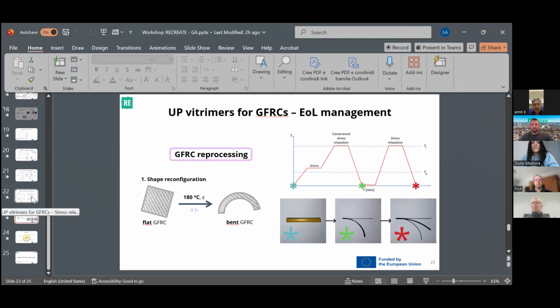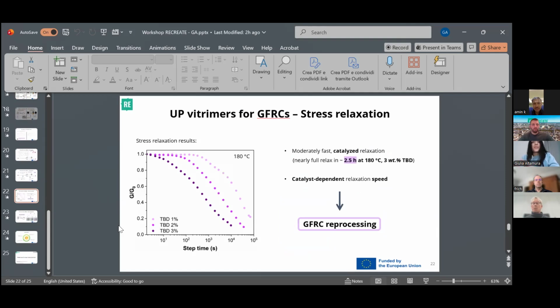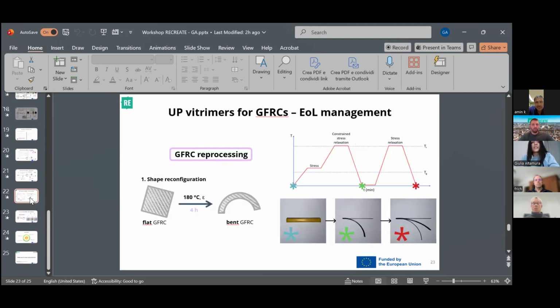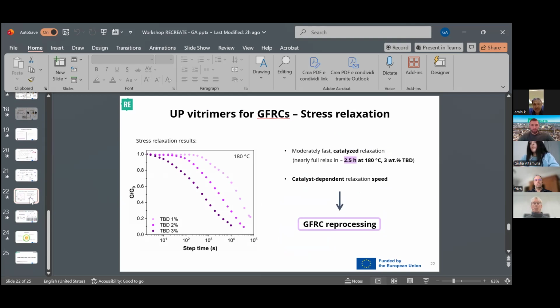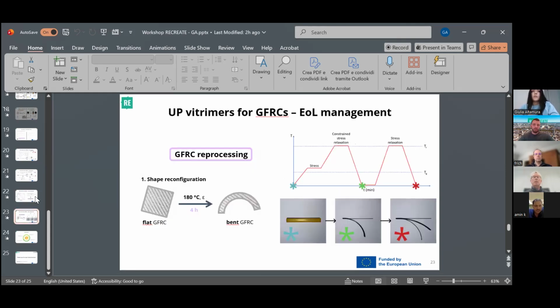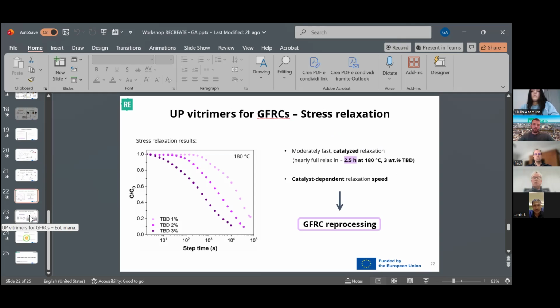Okay. Yeah, thank you. And as for the time, here we selected 4 hours, even though relaxation occurred in 2.5 hours. Let's say that we decided to stay safe. These times can be optimized by also taking in mind that relaxation tests are carried out in a rheometer that, of course, has an optimized heating system, while our oven doesn't have this kind of efficiency. But 4 hours can for sure be reduced. That's for sure. Okay, thank you very much. Thank you.